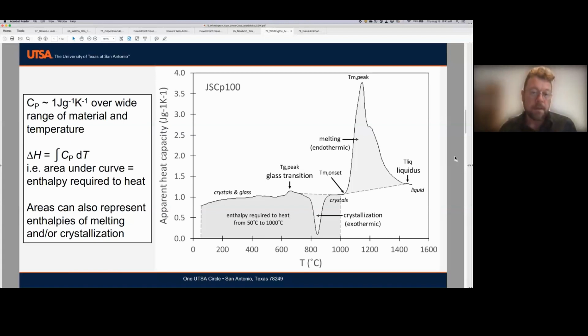But the additional stuff you see on this graph, we have a trough labeled crystallization and a peak labeled melting. These are enthalpies of phase changes, right? So an enthalpy change is the integral of Cp dT, i.e. the area under the curve. Or in this case, for crystallization, it's the area above the curve. But anyway, the example shown here is JSC, just straight out of the bucket, JSC powder. It's a mixture of crystals and glass to begin with. The heat capacity is around 0.8 joule per gram per Kelvin.